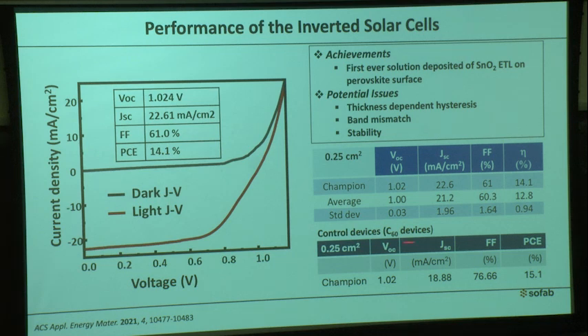We also made a control device depositing C60, which is the benchmark electron transport layer for PIN architecture. For the control, we got 15.1% efficiency, and this efficiency for the tin oxide device is not that far away.